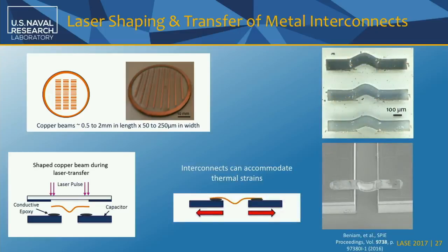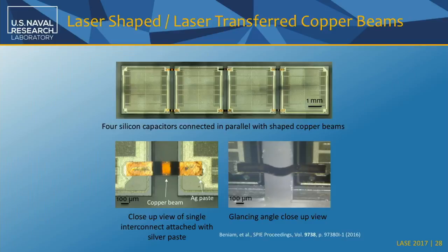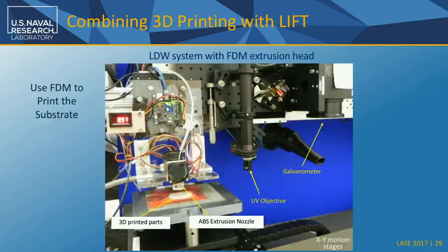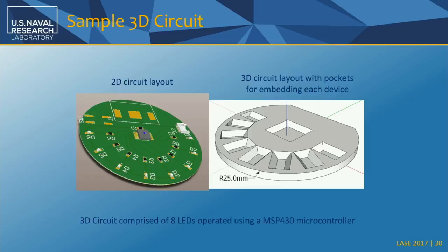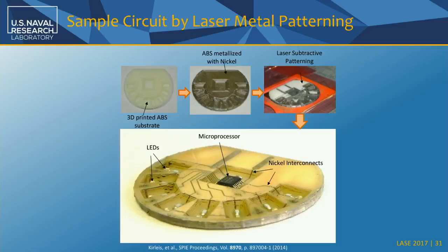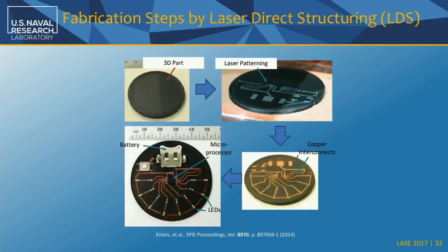And here are examples of some of these interconnects that are solid metal. This is no longer a paste that we use. We're actually using copper foil. And here's a circuit that we can actually demonstrate, making those interconnects. And the last thing is we can combine the laser transfer with additive, in this case, fused deposition modeling. So in the Z station that we have, we can add now an extrusion head, and we can now design a part, fabricate it, and put the devices in. In this case, we did the interconnects by plating first and laser removing. But in this case, we use laser direct structuring, where the resin that we print actually has metal particles that you can expose with the laser, and then you can electroplate, and now you can add your circuits.